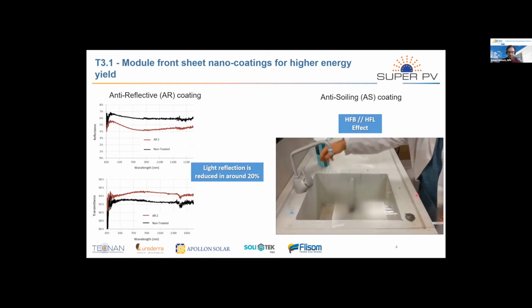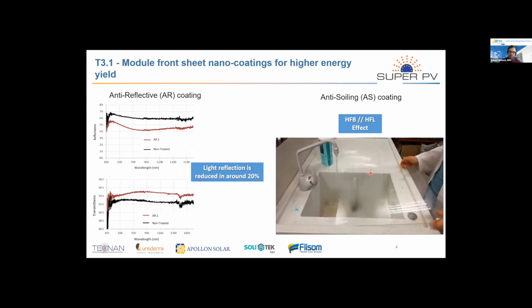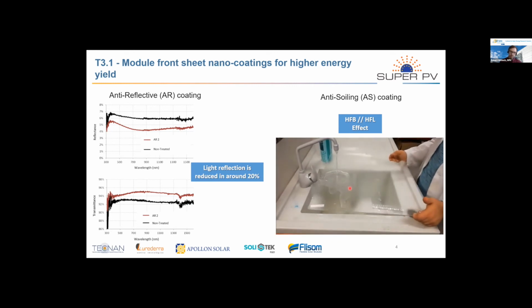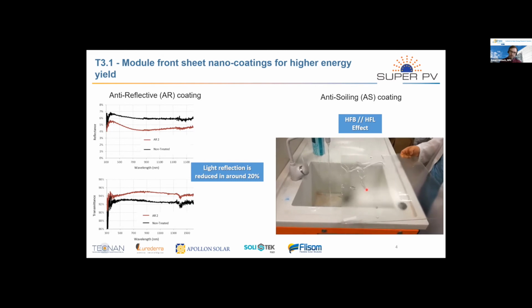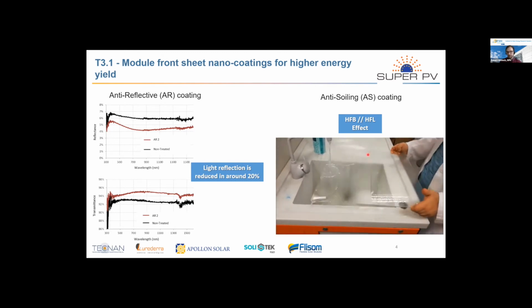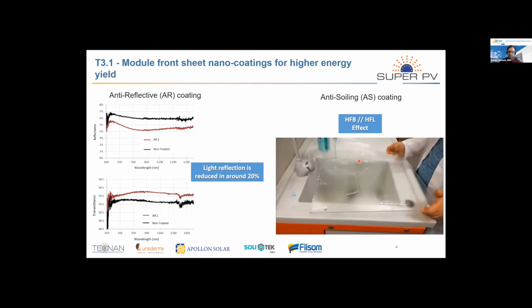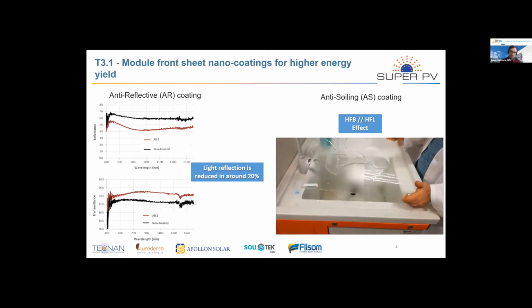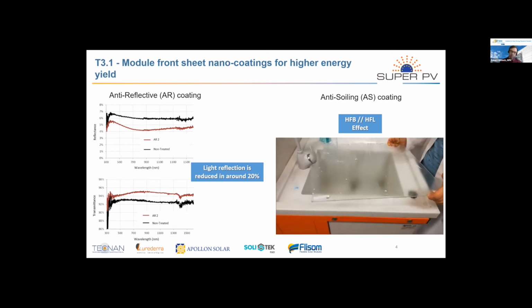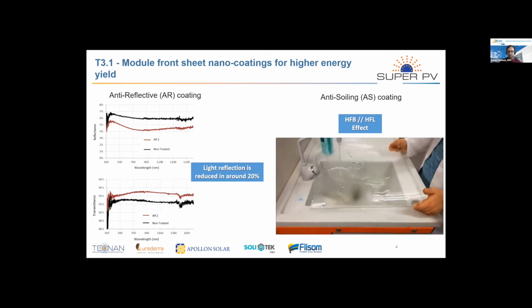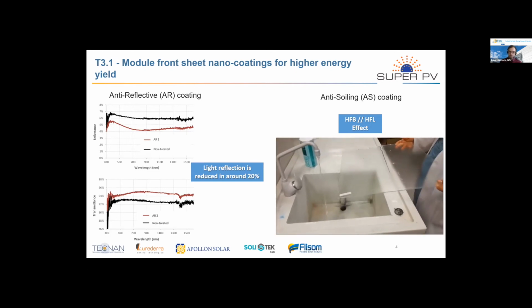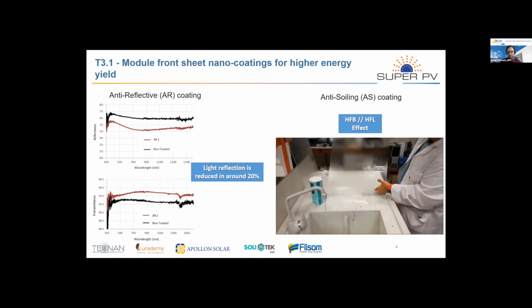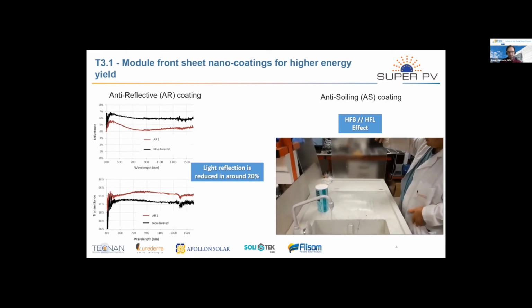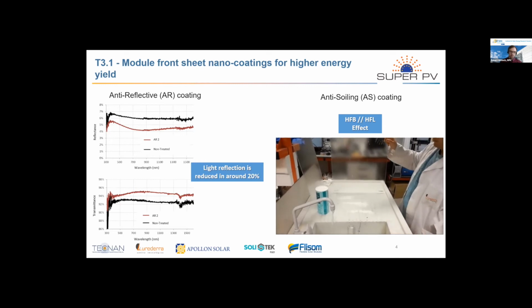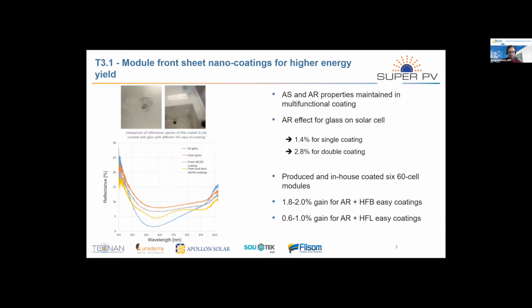So here we have a glass. The left-hand side is coated with this HFB coating. So here we have really a repelling effect of the water on the surface. And the right-hand side is coated with this HFL coating. And here we can see that the water starts to wet this entire surface of the glass. So both effects are possible with this nanocoating solution.